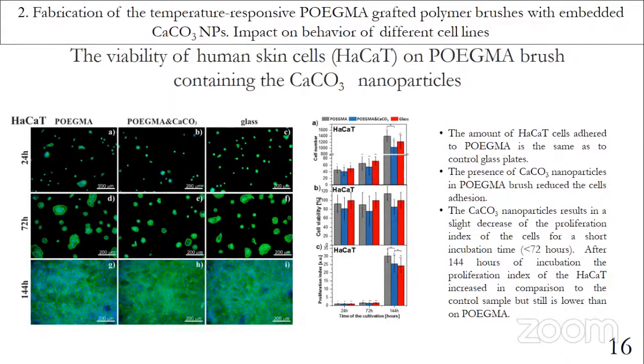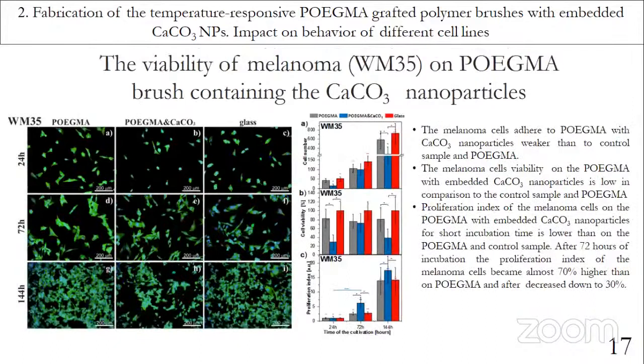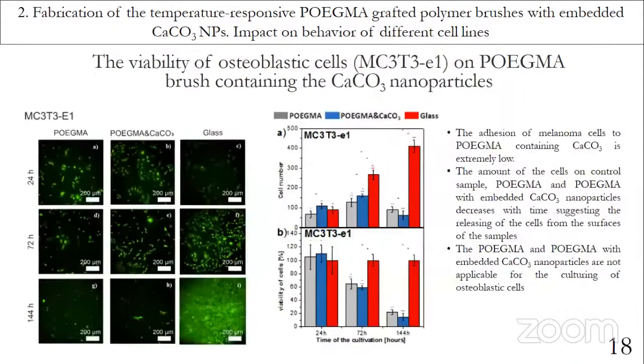Human skin cells, melanoma, and osteoblasts. And it can be postulated that the impact of polymer and polymer grafted brush coatings with a low concentration of embedded calcium carbonate nanoparticles strongly depends on the type. In contrast to the non-adhesion properties of polymer-based coatings reported before, we did not find a difference in cell adhesion for 24 hours of incubation on control glass surface and polymer coatings for all studied cell lines.